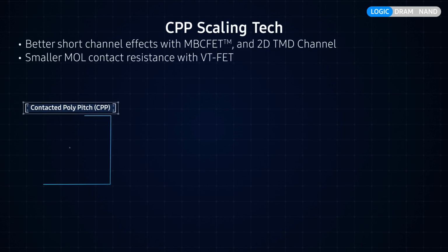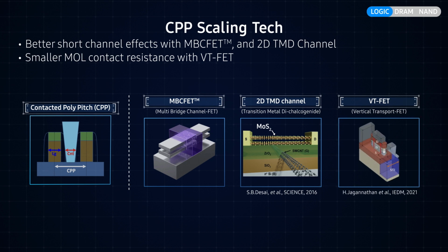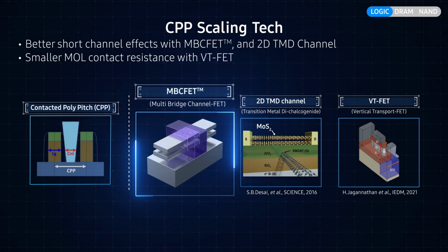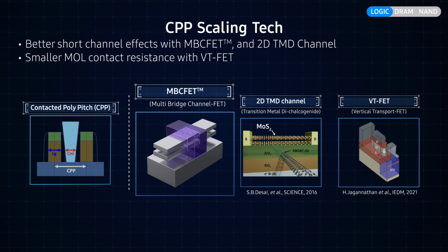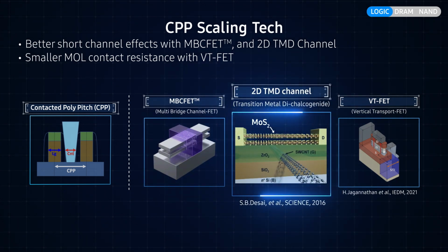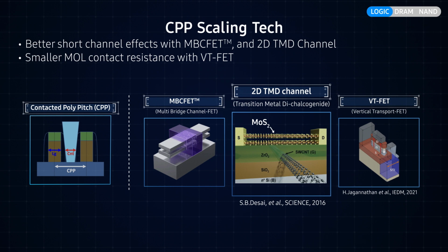One approach is to decrease gate length without suffering short channel effect. The other approach is to decouple the gate from the MOL contacts. First, let me discuss the gate length scaling approach. As mentioned previously, MBCFET provides the most excellent electrostatic control of the channel potential so that we can push down channel length further. The other is to adopt a novel channel material, two-dimensional transition metal dichalcogenide, or simply 2D TMD, which is only one monolayer thick, the ultimate thickness of the channel, which can provide ideal channel properties, such as high mobility and small parasitic capacitance.